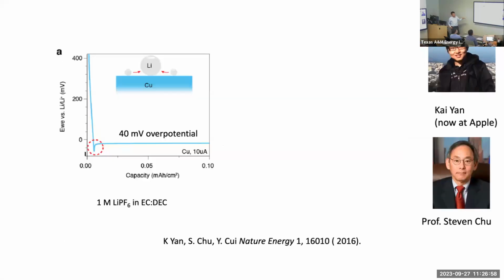Then we also ask the question, because we use copper as current collector, when you deposit lithium, if you look at this carefully, you measure the potential at a very low current density, you see a voltage dip, and then plating happens. This has 40 millivolt of overpotential needed to drive lithium metal nucleation on copper.